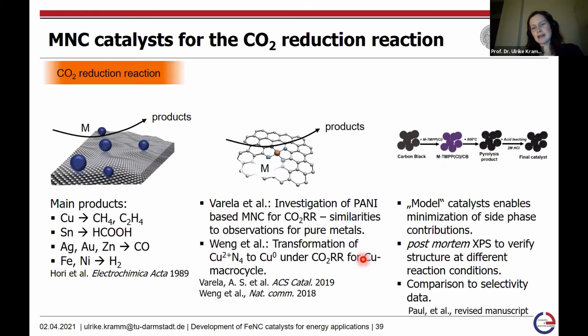So we basically then decided to select some model catalyst materials in order to minimize the side phase contributions. That means we used a carbon black in combination with very small quantities of a metal porphyrin. And the pyrolysis is also performed at low temperature, at 600 degrees C. That is basically a temperature before the disintegration of the metal-N4 centers during the pyrolysis takes place. But in any way, we also performed an acid leaching step so that if there might be some side products formed, we can leach them off before we then investigated the final catalyst materials.